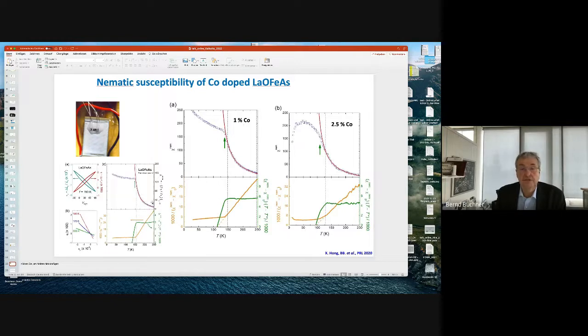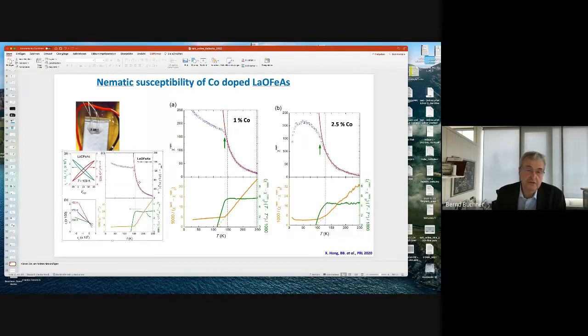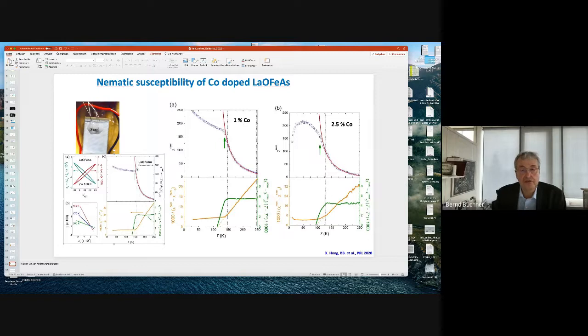and this is plotted here as a function of temperature. And it's not a surprise that again we see this strong divergence here at the structural phase transition. Now you can fit this by a Curie-Weiss law, which is shown here. So this is just in a different representation. You see this Curie-Weiss law. You see the Curie-Weiss temperature is slightly below, but close to this phase transition temperature. And this you can do now as a function of doping. So you always see this strong change of the resistivity upon tiny changes of the lattice.